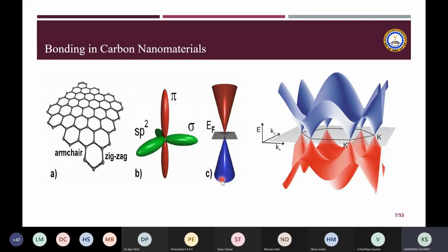This is a very typical Dirac cone structure of graphene. What you see here is that these two Dirac cones are meeting at a point and there is no band gap. So that gives a semi-metallic character to graphene. And of course, it is possible to tune this and introduce a very small band gap, and thus make it semiconducting. So you can tune it to change its property and then make it more useful.